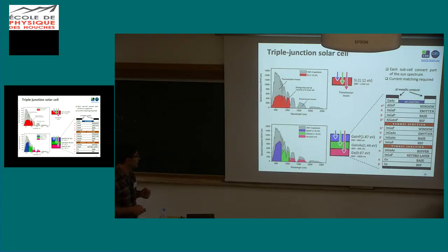This is a very conventional structure for a 3-junction solar cell with the 3 PN junctions. They all have the same structure. You have a window layer, so a wide bandgap semiconductor contact, the PN junction made of InGaP with an energy gap of 1.87, and then this back surface field, again in this case, is aluminum gallium indium phosphide.